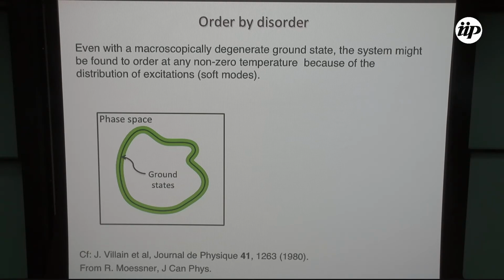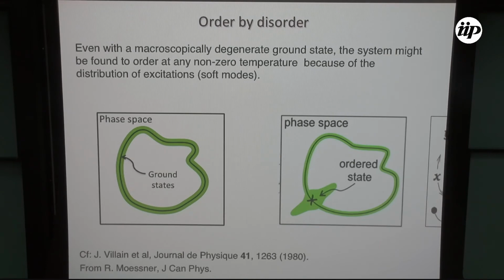But then if you're looking at the system at a finite, non-zero temperature, you need to ask not only what are the ground states, but what is the density of excitations around those states. If you have something like this, so this will be in phase space, this curve will be all your ground states, the black curve, and the green curve are the excitations. So if these excitations are more or less uniformly distributed, nothing particular would happen. But if you now have a case where there's one particular region close to your ground state that has a higher number of excitations, then as soon as you put in a temperature, entropy is going to favor, so in the free energy, the entropic term is going to favor being here.